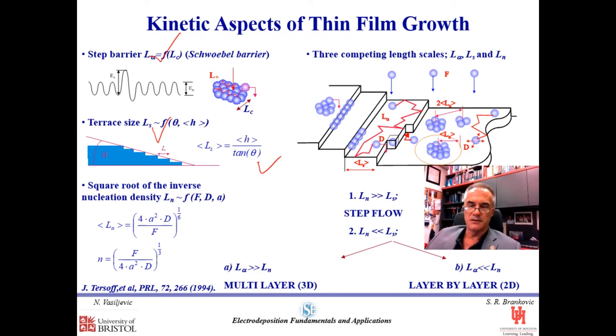The third length scale is L sub n, which represents the inverse square root of the nucleation density defined here, and which is a function of the flux, the deposition flux onto the surface, which also has a relation to the deposition current density. So these competing length scales and their mutual relation define the growth mode.